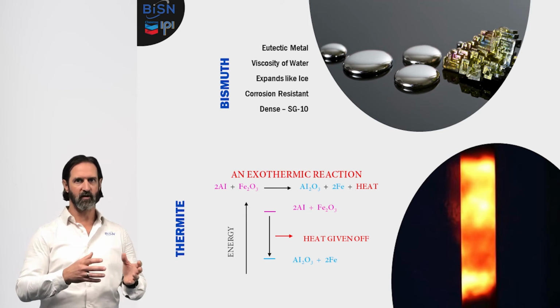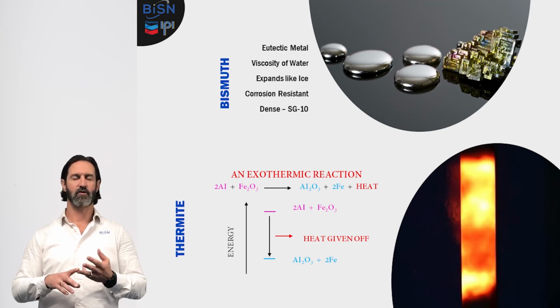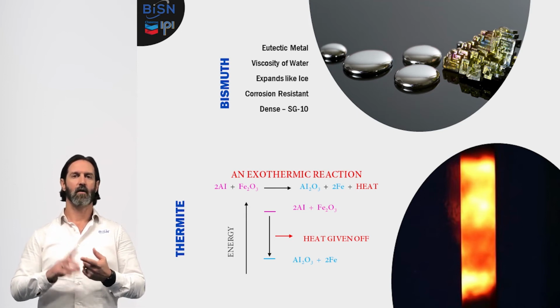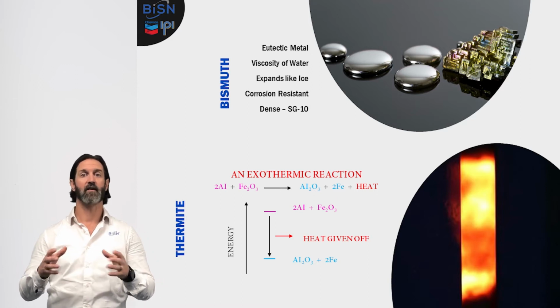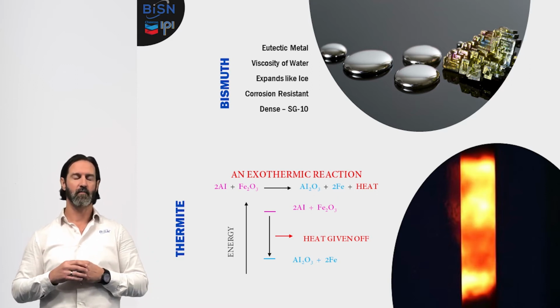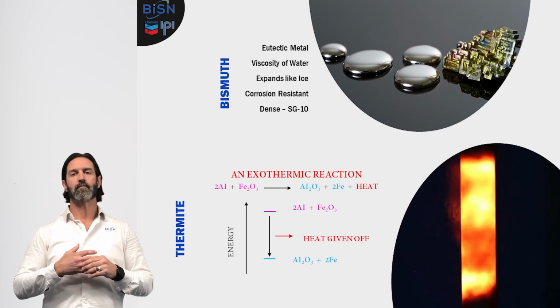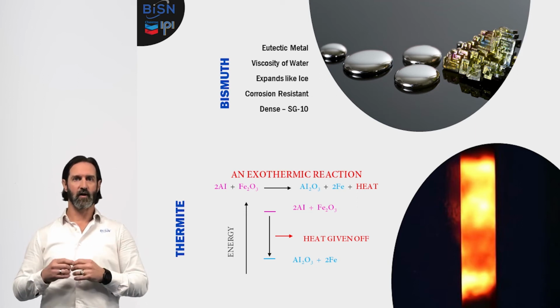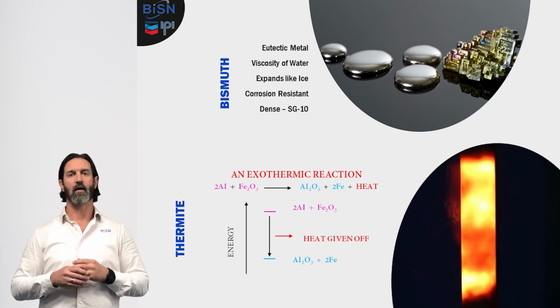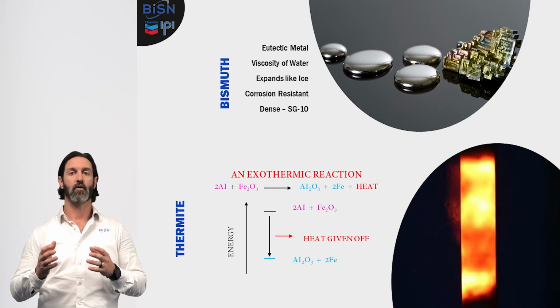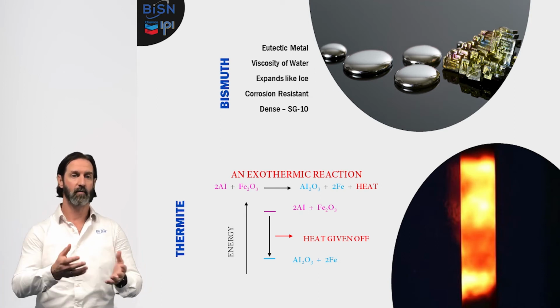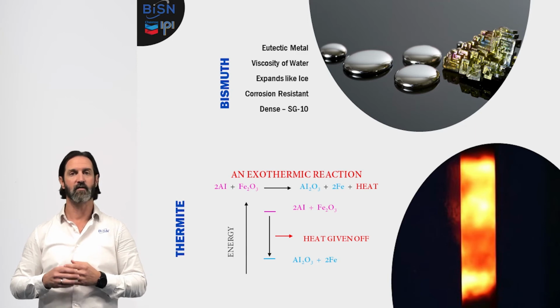So remember we talked about the cement, very porous and shrinks on solidification. Bismuth alloys actually expand on solidification and have zero porosity. The way we get these from a solid to a liquid then back to a solid again is we melt them down hole using an exothermic chemical reaction, modified version of thermite, as you can see there.